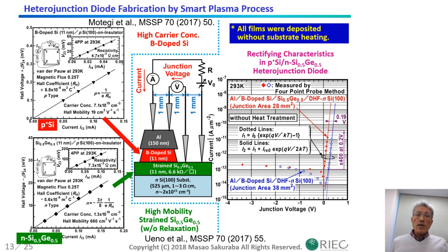Additionally, modulation effect by bandgap narrowing in silicon-germanium alloy has been successfully observed from the voltage shift. This is good news for us. By eliminating high temperature process, these results indicate a possibility that part of semiconductor device fabrication can be more simplified, that is, a smart process, while keeping device performance. For example, waiting time for heat up and cool down, and the cross-contamination problem caused by thermal diffusion, might be eliminated.